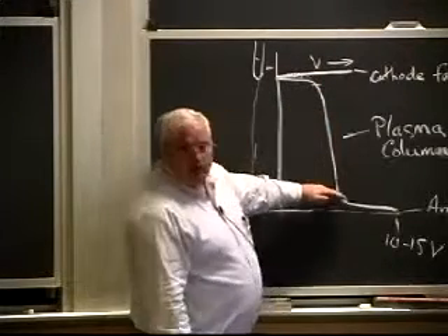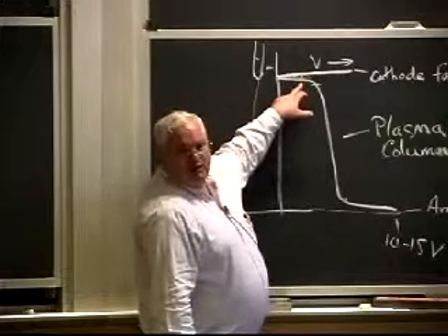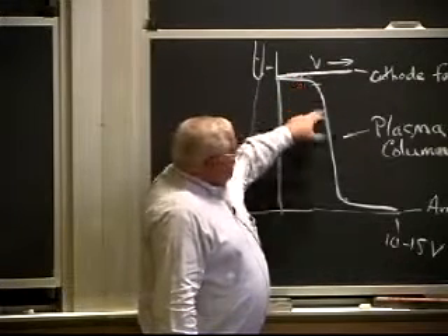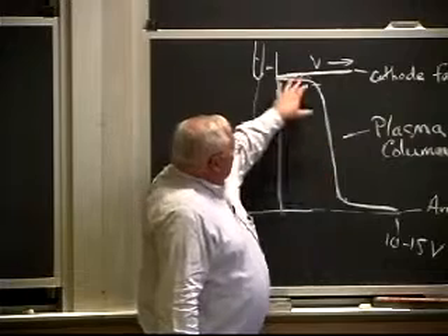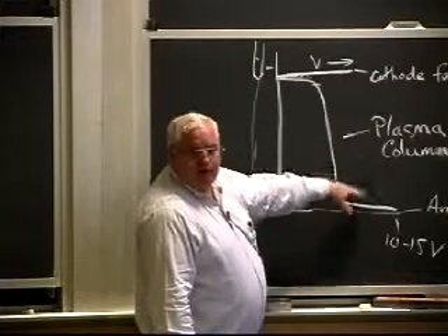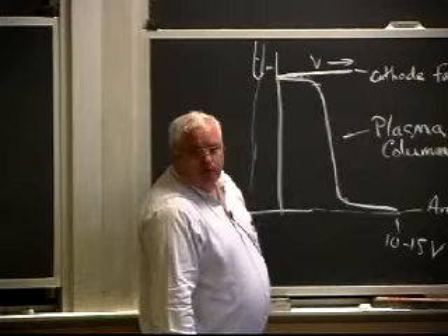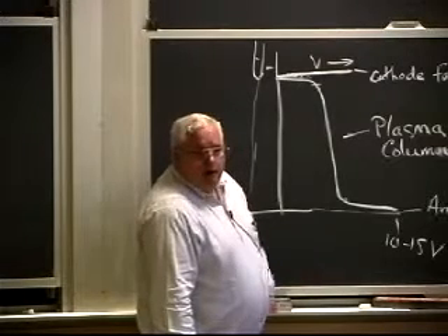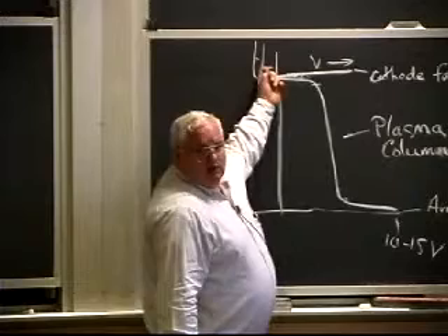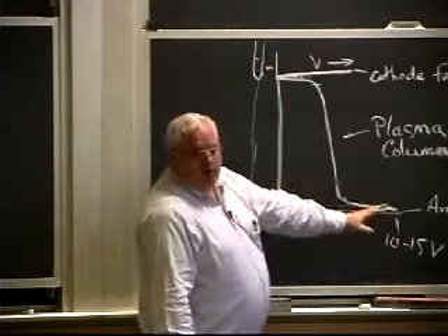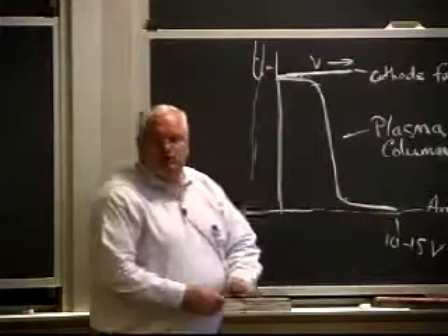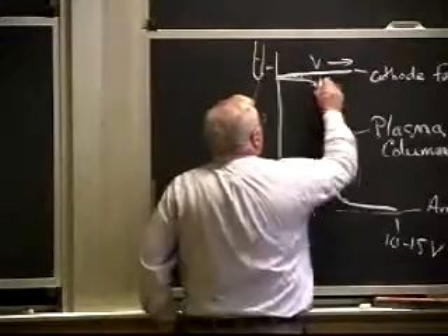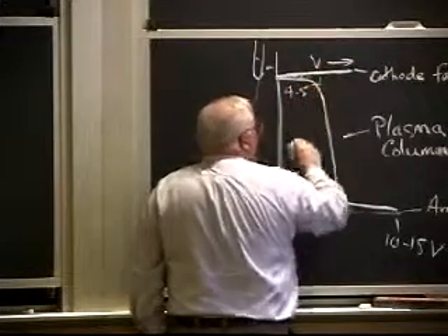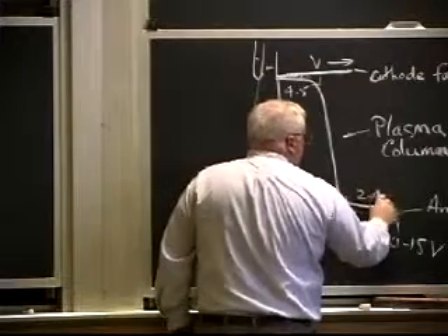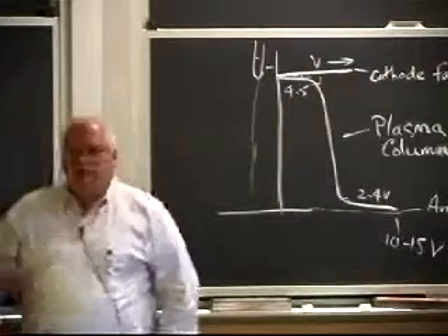The fall regions, these little regions, are only about 1/10 of a millimeter in length. So I could have 8 volts drop across the plasma, and in the other anode fall and cathode fall regions I would maybe have another 8 volts or 7 volts or so falling across there. If this was a steel electrode, this might be a 25 volt or 30 volt arc. But order of magnitude is a few tens of volts. These fall regions are typically 4 to 5 volts for the cathode fall, and the anode fall might be 2 to 4 volts. We'll get into some more of that later. It depends on the material.